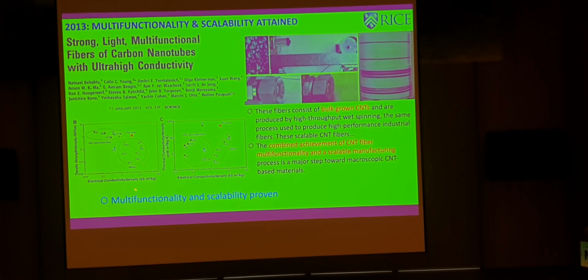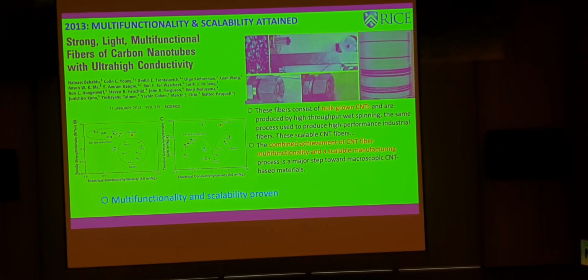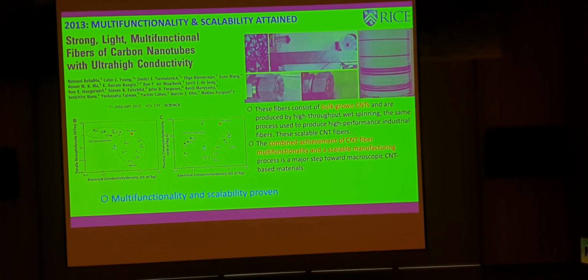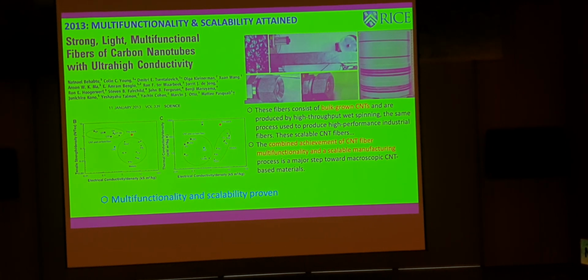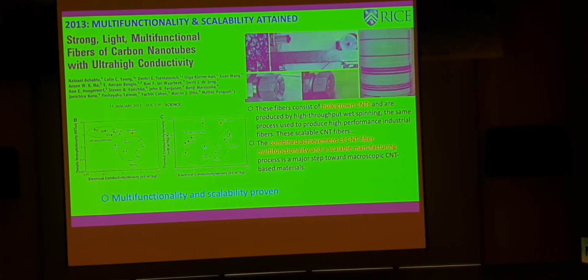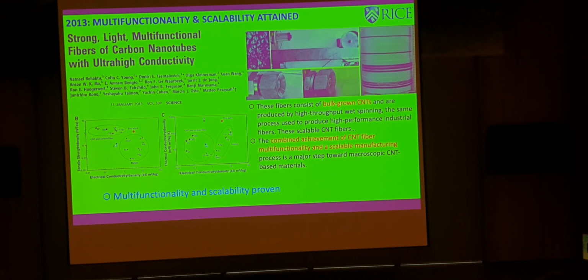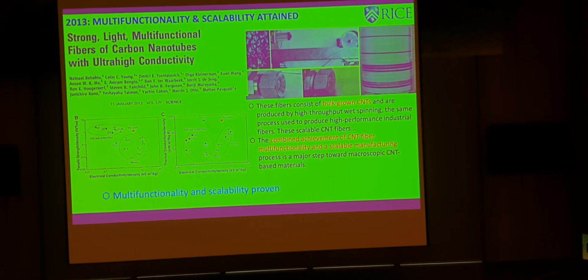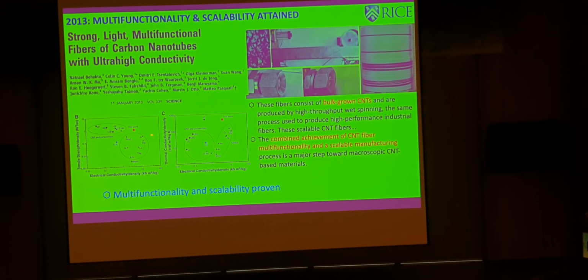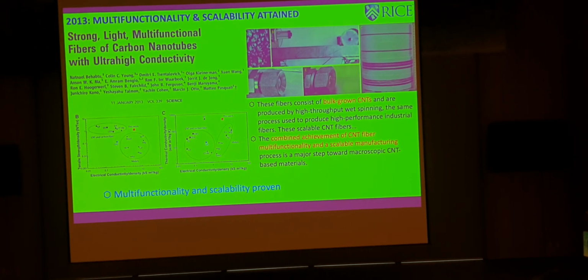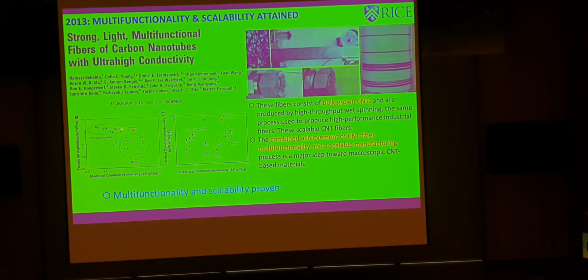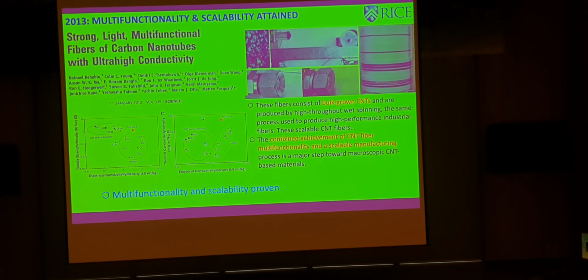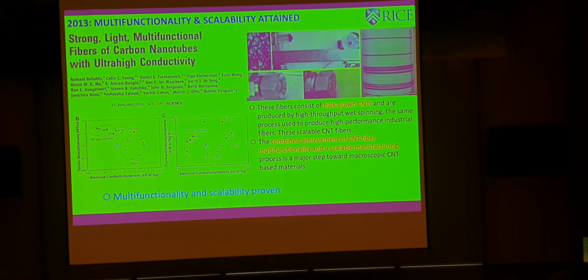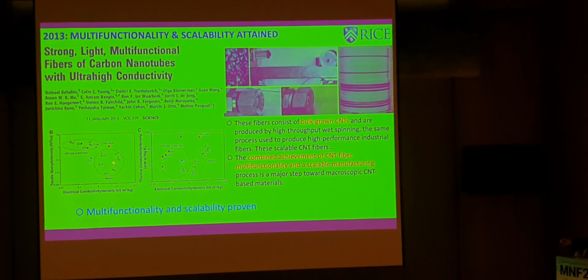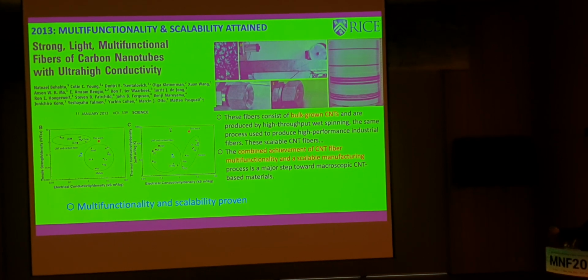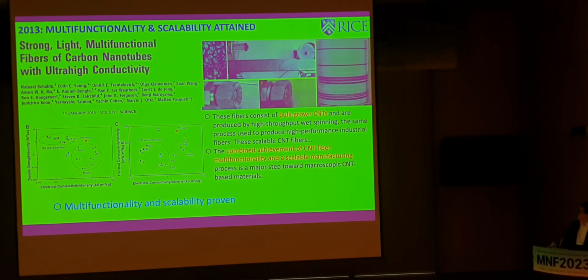So here you have a couple of Ashby plots. One is strength versus electrical conductivity. Another one is thermal conductivity versus electrical conductivity. These are specific, so normalized by density. But you see that in both cases, the fiber has multiple functionalities: in the ballpark of carbon fibers and other carbon nanotube fibers for strength, in the ballpark of conductivity for metals, higher thermal conductivity, and so on.